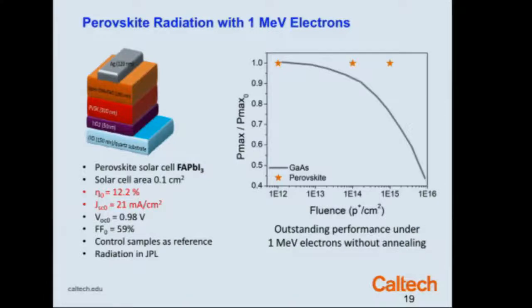These aren't particularly efficient. We've made other cells with efficiencies as high as 20%. They're not as high as the gallium arsenide cells. But the specific power, the power per unit weight, is quite remarkable. Moreover, as we irradiate with electrons, this is done at the radiation facility Dynamitron at JPL, here's the gallium arsenide data. We're losing half the performance. Here's the perovskite data, completely unchanged in its power. This is without any radiation shield.